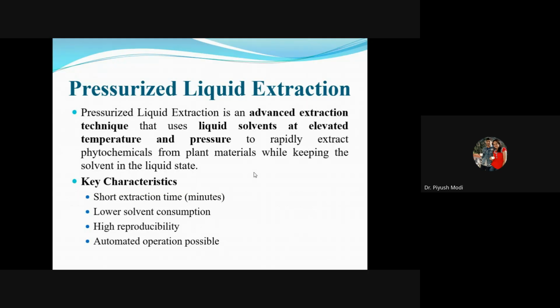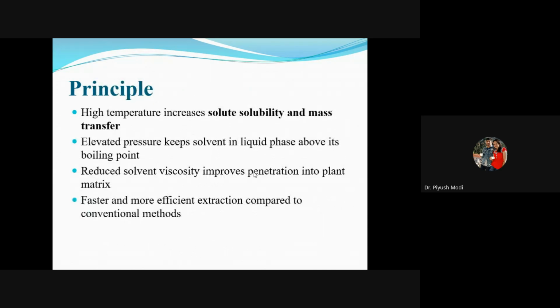In this advanced extraction technique, the solvent is elevated in both temperature and pressure. We use this method for phytochemicals that are not heat sensitive. It is a short-time extraction method with lower solvent consumption, high reproducibility, and automated operation is possible. In principle, for solute solubility and mass transfer, the solvent is kept in the liquid phase above its boiling point. We increase the temperature, which reduces the solvent viscosity and improves penetration into the plant matrix, and the oil comes out from the oil gland.